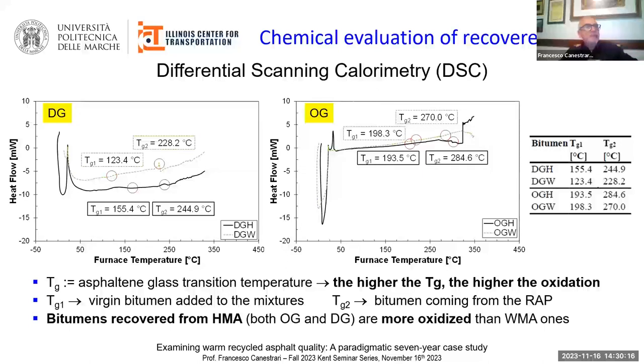The higher values of the glass transition temperature obtained for binders recovered from dense-graded hot mixtures imply higher oxidation. The Tg values for hot and warm open-graded mixtures are similar, because in this case, the oxidation is mainly due to the in-service long-term aging due to the weather effect.